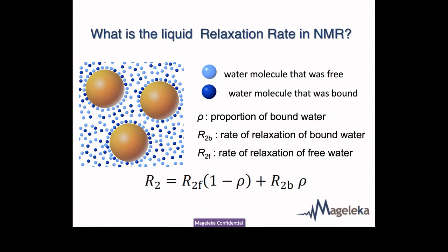But what happens is this is a very dynamic system, and any of the molecules that are on the surface can exchange with any of the ones in the bulk. And you can see the different colors corresponding to ones that are exchanging, going backwards and forwards. All the blue and dark blue water molecules are exactly the same, but they're in this dynamic equilibrium between each other. That means if you measure the relaxation time of a bulk water molecule, it's a dynamic average of what happens at the interface and what happens in the bulk solution.